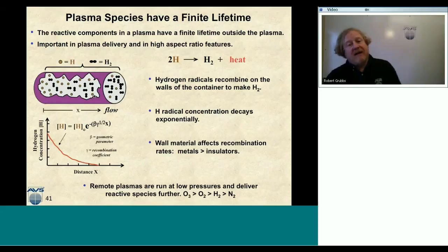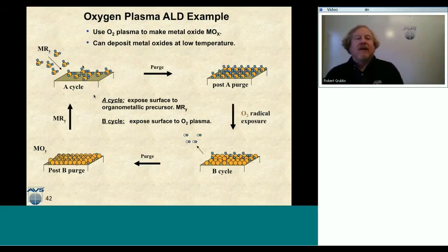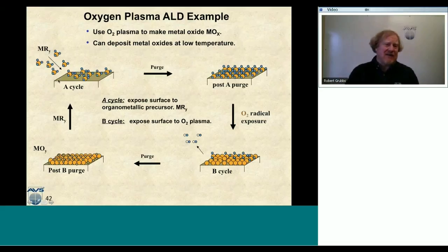Now let's look at oxygen plasma as an example. And so we have O2 plasma here to make some sort of metal oxide. So I come down here onto a surface with a metal organometallic precursor. It will probably sit in a physisorption state on the surface. Now, it won't chemically bond with the surface. It'll be in a physisorbed state. I'll purge it after I've reached surface saturation, and I'm left with maybe this organometallic surface. And then when I come down with the oxygen radicals, it'll strip away the organometallic or the hydrogen that's in that molecule and make the oxide.